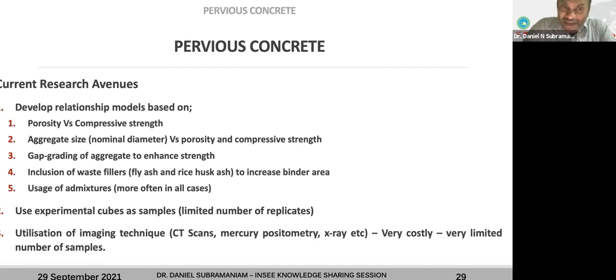Then gap grading of aggregates, rather than just using one size of aggregates, you can use, for example, 5 to 10 and 20 to 25, something like that, so that you can mix them. And the inclusion of waste fillers like fly ash or rice husk ash. Then you have coir used, sometimes coconut shell husks are used, so there are a lot of other waste materials. And then there are fibers used inside the pervious concrete, and then use of admixtures.